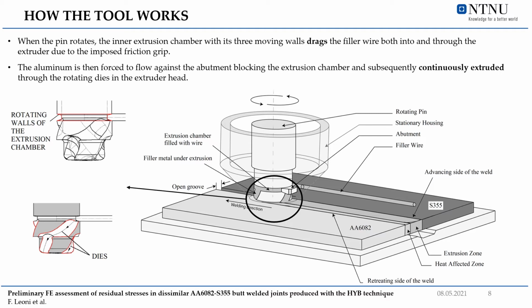Metallic bonding between the filler metal and the base material occurs as a result of these two contributions, along with oxide dispersion. By taking into consideration the mass balance involved, the extrudate flow rate can be adjusted in such a way that the groove between the plates is filled with solid aluminum in a continuous manner.